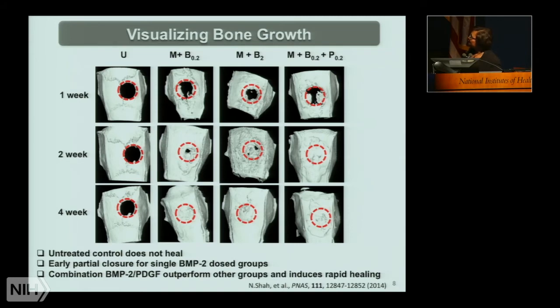Here you can see micro CT of the bone regeneration process. Here's our untreated control, and you can see the critical defect is, of course, not closing in this rat cranial defect model. However, if you look at the release of 0.2 micrograms of BMP2, you can see that you are getting closure of the critical defect, and it seems to be fairly rapid. With the 2 microgram dose, we've increased the dose by 10, but haven't really changed anything about the nature of the closure of this wound over that time period, which suggests that there is a limit to how much more can be impactful.